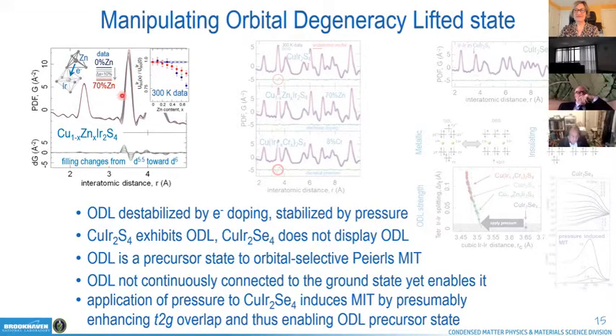And it also serves as proof that what we see is indeed electronically driven. Another aspect of it is that when you measure the Debye-Waller factor of the iridium site as a function of zinc content at room temperature, you see that it drops dramatically, which suggests that whatever distortion there was, which is uncorrelated structurally, gets removed from the system.